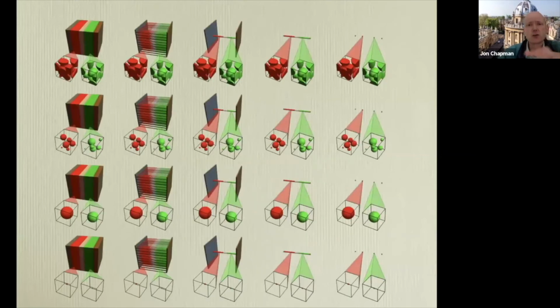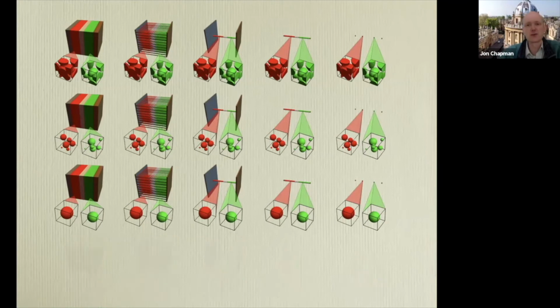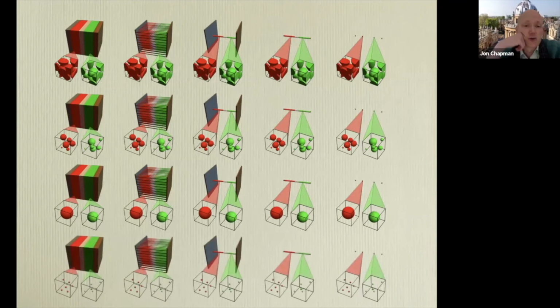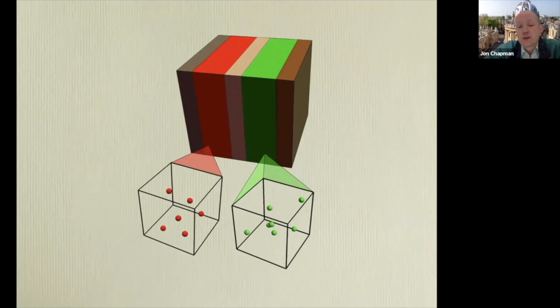You can, of course, do these asymptotic limits in different orders. So I talked about taking the high conductivity in the current collector first and then taking high conductivity in the electrolyte. You can do those in a different order, or you can also do the microscale ones in a different order. So instead of going to a single particle and then saying it's fast diffusion in the active material, I could say, well, I'm still keeping a collection of many particles. So I've got a distribution of particle sizes, but diffusion is fast so that I'm only solving a collection of ordinary differential equations for them.